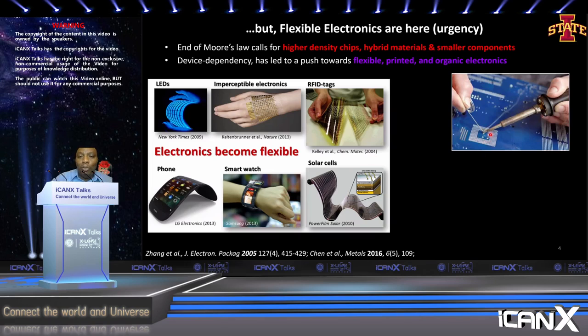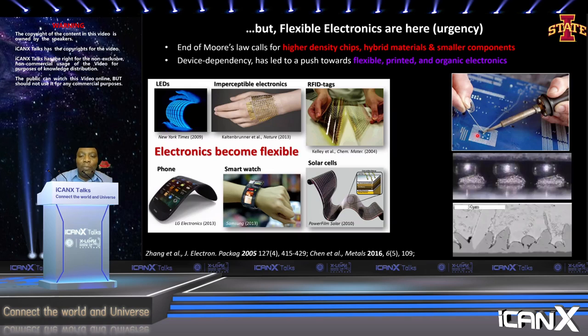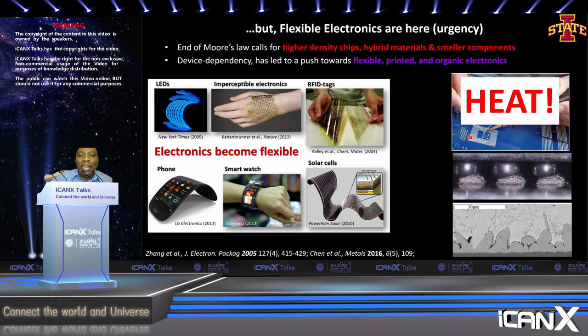And this solder has problems that are 5,000 years old. Since the solder was invented during the Roman reign, we have problems that we have never solved. Some of those problems are structural, like defects. Others are chemistry, where we have interfaces that form intermetallics, mixing of metals, and these intermetallics do grow and can cause problems in whatever we try to join. But above that, when we go to flexible and smaller devices, we have the problem of heat. And how do we overcome that heat?